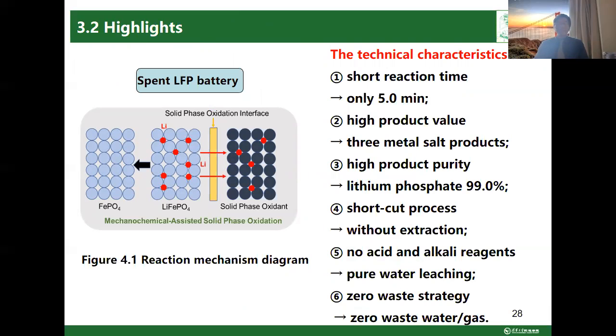First, taking the spent lithium iron phosphate battery as a research object, high purity lithium phosphate, iron phosphate, and three metal salt products can be obtained by using mechanochemistry-assisted solid phase oxidation, pure water leaching, and chemical precipitation. The technical properties of the process include several aspects: short reaction time, high product value, high product purity, a short recovery process, no acid and alkali reagents, and zero waste residue can be achieved through this technology.